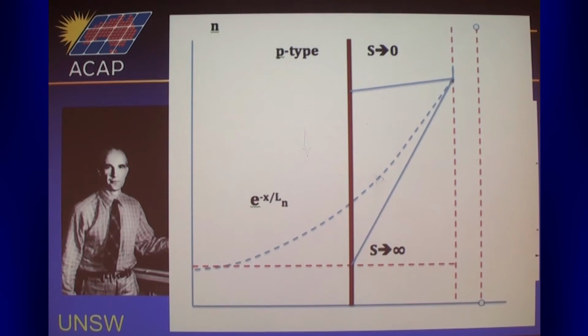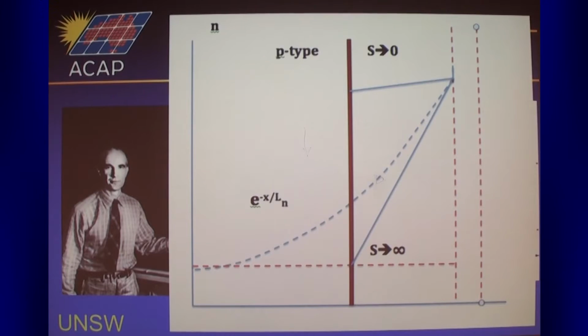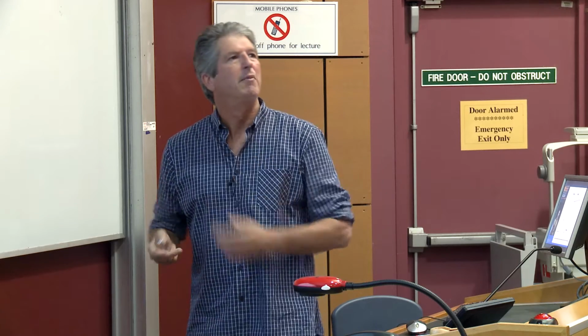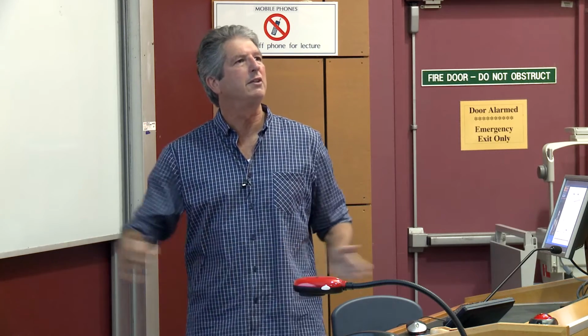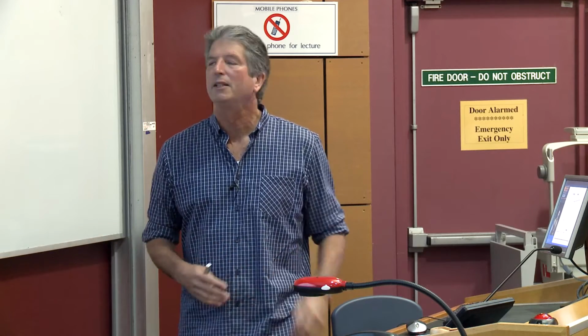If you go the other direction, if you have a perfect surface, a surface that's inert for minority carriers, you have what's called a zero surface recombination velocity. It doesn't matter how many carriers get to that surface, they're just not going to recombine. There's no process for them available there to recombine. And what happens there is you get an enhancement of the carrier concentration throughout this region here. And you'll note the gradient here is reduced very substantially. So very much less, like it might be 5 or 10 times less in this drawing here. But that means 5 or 10 times less current flow, so your knee voltage can increase accordingly.